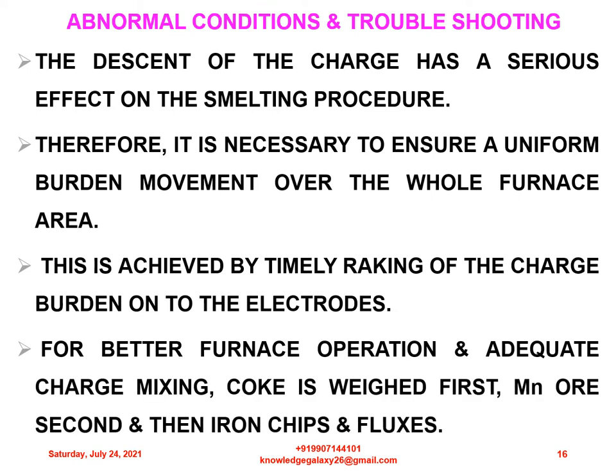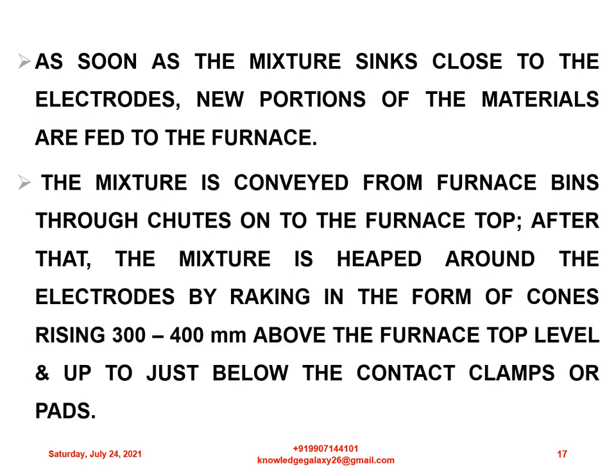For better furnace operation and adequate charge mixing, coke is weighed first, manganese ores second, and then iron chips and fluxes. This is very important from the point of view of starting the furnace operation — which material is to be weighed first and which to be weighed later. As soon as the mixture sinks close to the electrodes, new portions of the materials are fed to the furnace. The mixture is conveyed from furnace bins through chutes onto the furnace top, then heaped around the electrodes by raking in the form of cones, rising 300–400 mm above the furnace top level and up to just below the contact clamps or pads.